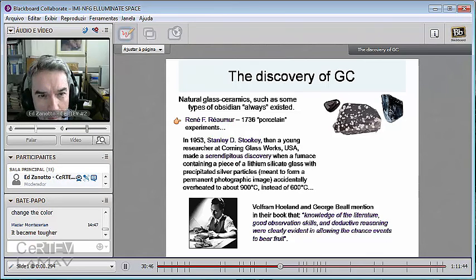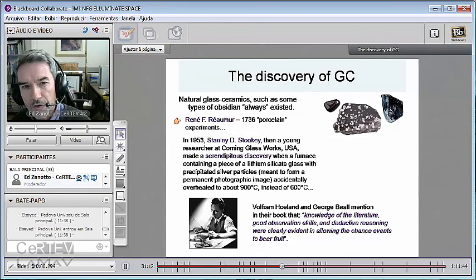It deformed. It crystallized from the surface a little bit, partially crystallized, but the residual glass completely deformed. So he ended up with a partially crystalline material but completely deformed. It was no longer a bottle. That was a very interesting experiment, and he published that paper. I have the reference somewhere in the proceedings of the French Academy of Sciences or something like that. He published that paper, and he shows all the details of the experiments.